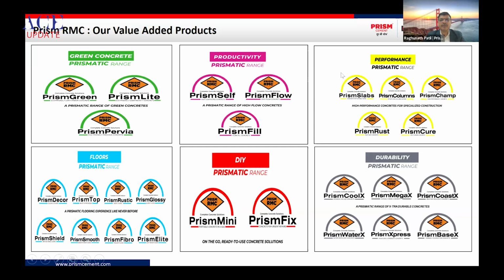Further, we have Prism Column. We have developed this product especially for column concrete, because at most construction sites the column quantity is very small, and enough precaution is not taken while casting the columns. Most of the time, to speed up construction activity, the construction industry needs to de-shutter the columns early, and the column is one of the important members in a structure. To take care of this, we have developed a special column concrete which we can pour to a height of 2.4 meters without any segregation, and the workability retention of the concrete is up to 4 hours, because there is no need for any addition at the site. Even if it takes more time to cast the concrete at sites, the concrete retains workability for 4 hours.